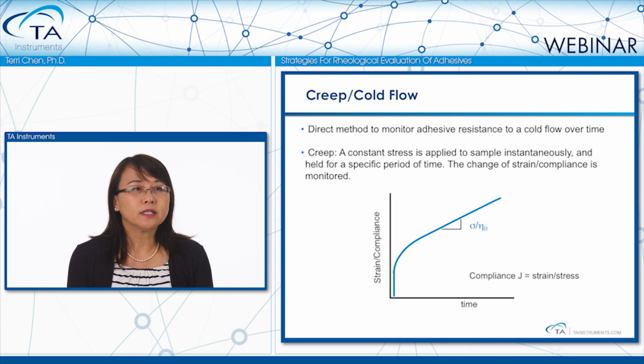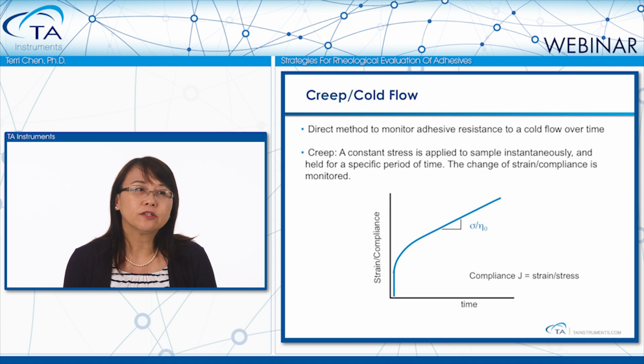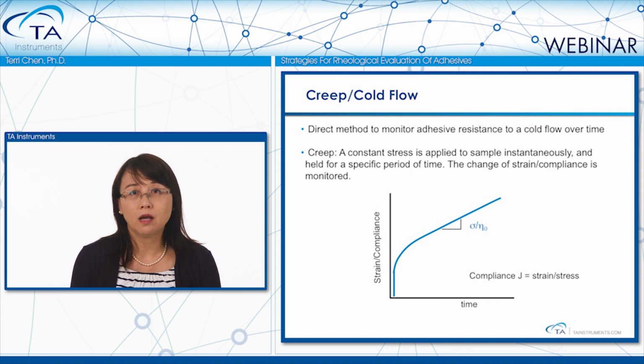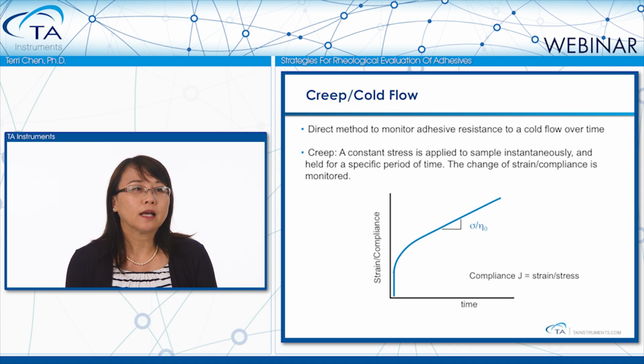Alternatively, shear resistance property can also be evaluated using a transient experiment, which is a creep test. Actually, creep is a more intuitive method to monitor cold flow of an adhesive. In a creep test, a constant stress is applied to the sample instantaneously and held for a certain period of time. During this time, the change of strain is monitored. Sample compliance is calculated from the ratio of strain over stress.